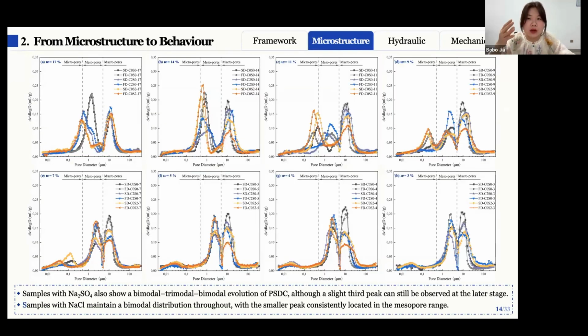And from now on, it's about the salt effect. In the following analysis, to better highlight the effects of salt and drying, only the results from the top part of the sample will be presented, because under slow drying, all parts of the samples show very similar PSD curves, while under faster drying, the top part is the most affected region during evaporation.